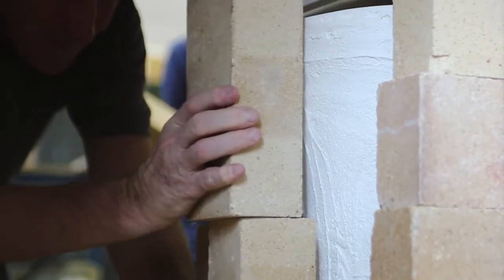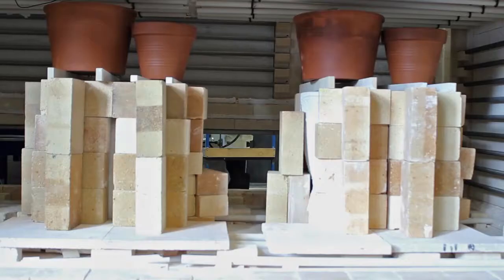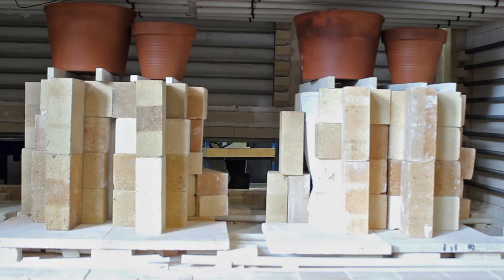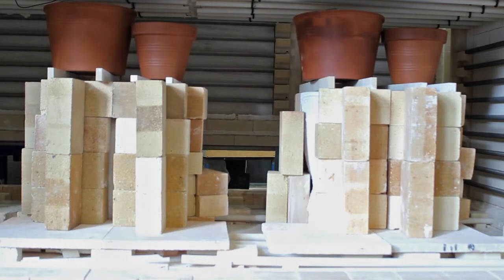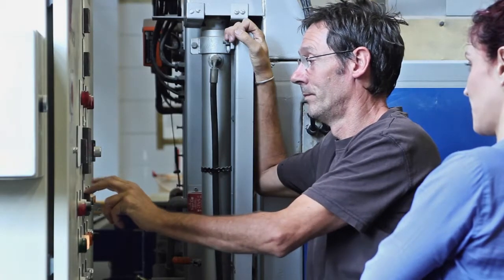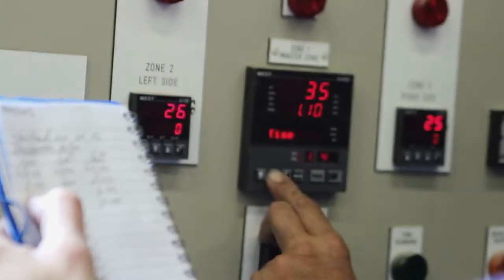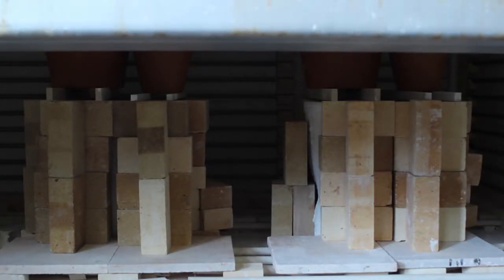The firing in total takes 41 days. It takes about 2 days or 2.5 days to reach the peak temperature, which, as I mentioned, is 825. And it soaks at that temperature for 12 hours, 13 hours, and then it starts cooling down. It cools down fairly quickly to 700 degrees, and then from 700 degrees to room temperature, it takes about 38 days. This is the annealing process of glass, so we're trying to even out the temperature throughout the piece, so the piece will not get thermal shock.